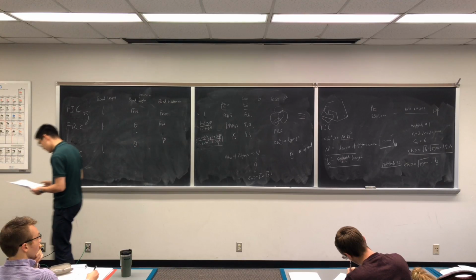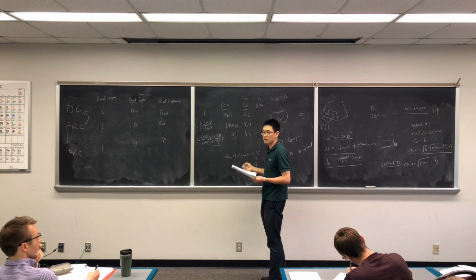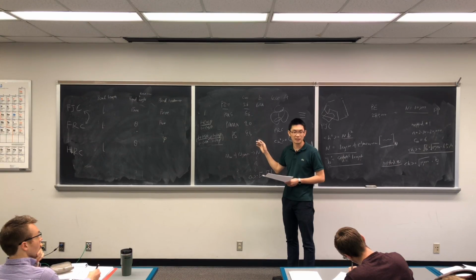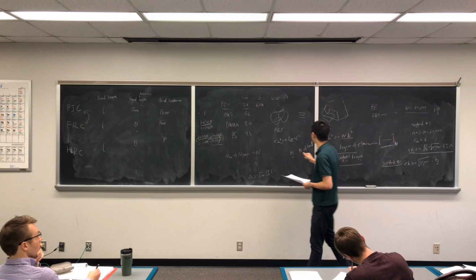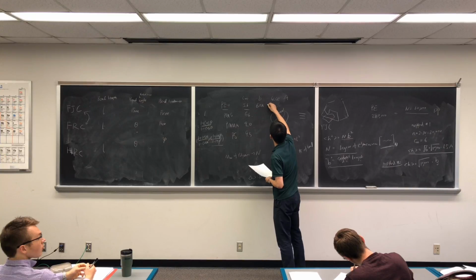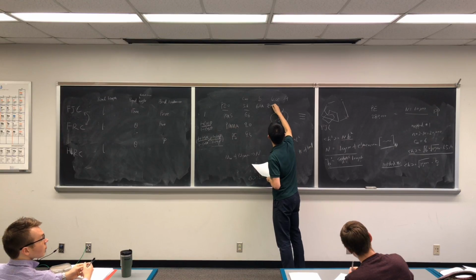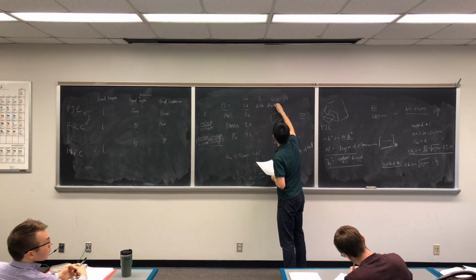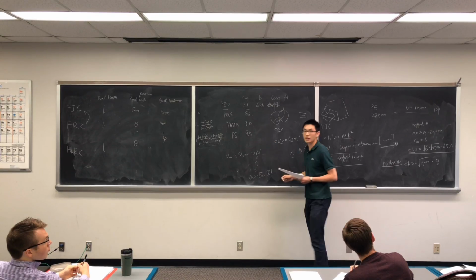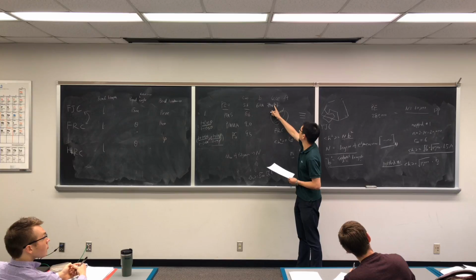So B for PEO is about 6.0 angstrom. That's about 4 times bigger than a typical carbon-carbon bond, right? Because you think this way, PEO has the structure of... I'm missing a C. Okay, so theoretically, you would expect 1 bond, 2 bond, 3.